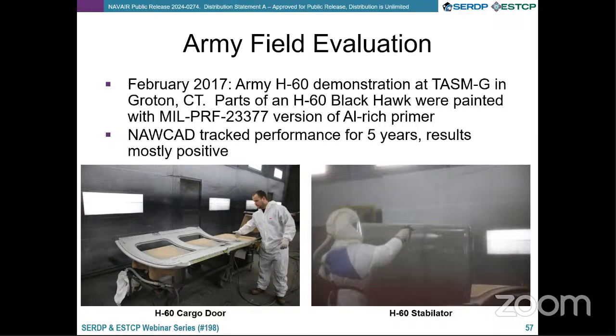So we had sent a team out to inspect those for 5 years and look for things like coating delamination, corrosion around fasteners, damage from the door sills and use and so on. And the results we found were mainly positive, comparing the test primer against the legacy.